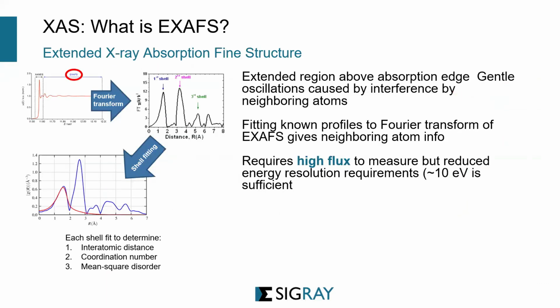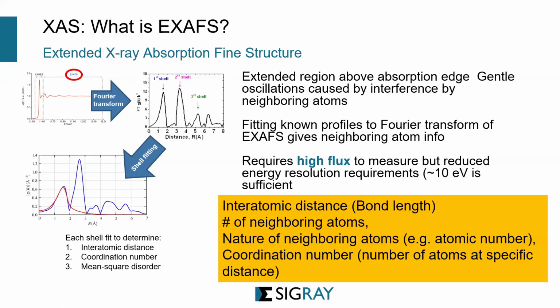So now what is EXAFS? It is the oscillation that we talked about. It is caused by the interference from the neighboring atoms. If you look at all this oscillation, you do not see much information, but when you do a Fourier transformation on that spectrum, you find that you can distinguish the information that comes from the first shell versus the second shell versus the third shell. From there, you can derive your interatomic distance, your coordination number, and also the mean square disorder. Therefore, EXAFS gives you bond length, number of neighboring atoms, the atomic number or the nature of the neighboring atom, and the coordination number, or the number of atoms at a specific distance.